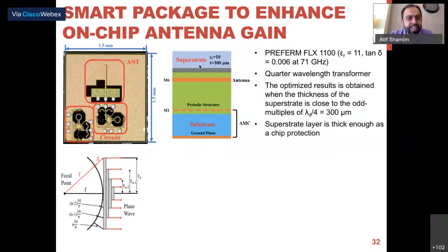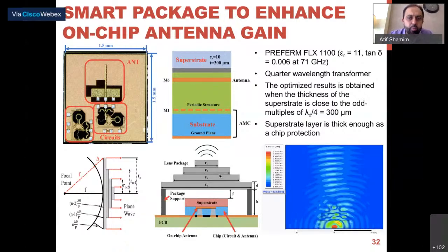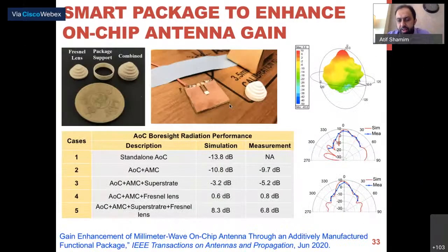Now, these are the printed lens, the support layer and the superstrate layer. And we got an immense boost in performance by just smart packaging. Imagine this chip was supposed to be packaged without any performance boost, a standalone chip, which was lossy, sitting on lossy silicon, and had poor gain. We actually went all the way to a positive 8.3 dBi, or in practice 7 dBi of gain, which is almost a boost of 19 to 20 dBi. So that's the example of the smart package. Okay, we did a number of other inks quickly, not going into details.